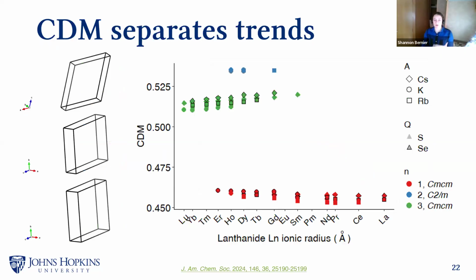And this is what it looks like when we apply the cubic deviation metric. Same axis down here, although it's inverted the other direction, where we have the lanthanides on the bottom, and then our value on the y-axis is the cubic deviation metric. And what you'll see here is that, instead of having a long, smooth relationship between these, we instead have grouping and clustering. And the really interesting thing to look at from this perspective is that I'll remind you the n=1 and n=3 homologies have the same space group. They're both orthorhombic. And yet, the cubic deviation metric tells us that the 2 and the 3 homologies are actually more similar to each other than they are to the n=1.